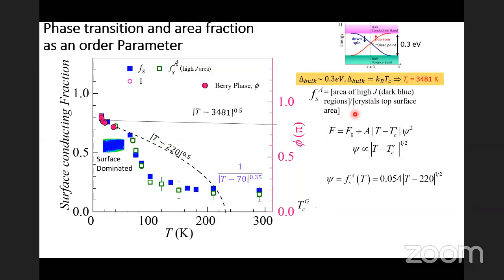Okay. And from Ginzburg-Landau theory, if there is a critical transition temperature where there is a transformation, the order parameter should go as T minus Tc raised to the power half. So here is a fit of the data of this fraction with a critical temperature of 3481, which is actually not fitting the data. But you can see that this fraction fits very well with a critical transition temperature of 220 Kelvin. And we believe this is the mean field transition temperature because along with your surface conducting fraction, there is a normal fraction appearing in the bulk because of excitation of the carriers in the bulk by the selenium vacancies. So the actual mean field transition temperature is 220 Kelvin, and this fits the initial part of the data where the data is surface dominated by the topological charge carriers.